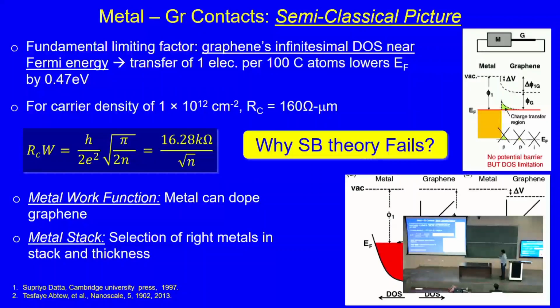Now what we did, we basically questioned this because we felt that there is a failure in Schottky barrier theory. Why was there a failure? So this will work. When this works, if you lower the temperature, what happens is that the thermionic tail goes down, and because of that the thermionic emission probability goes down, right, and therefore the conduction will come down, the contact resistance will appear to be higher, right. So if you lower the temperature, you measure higher resistance if there's a Schottky barrier.